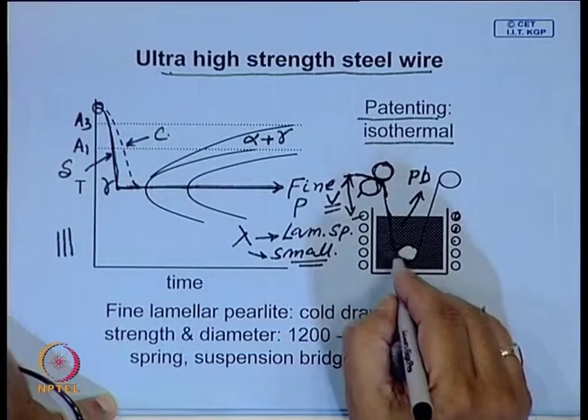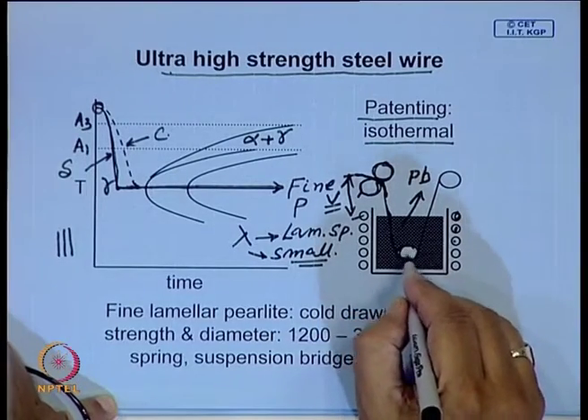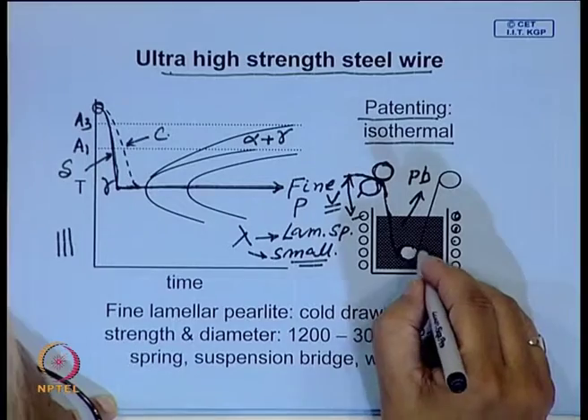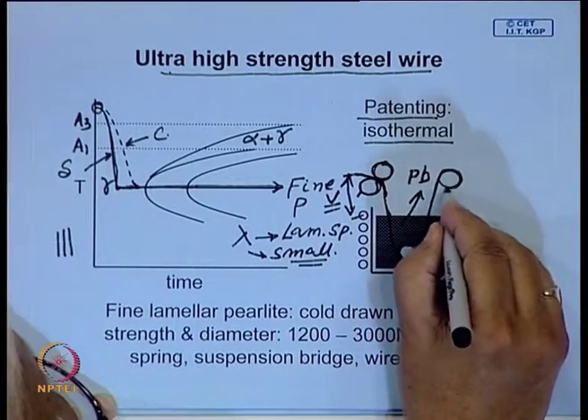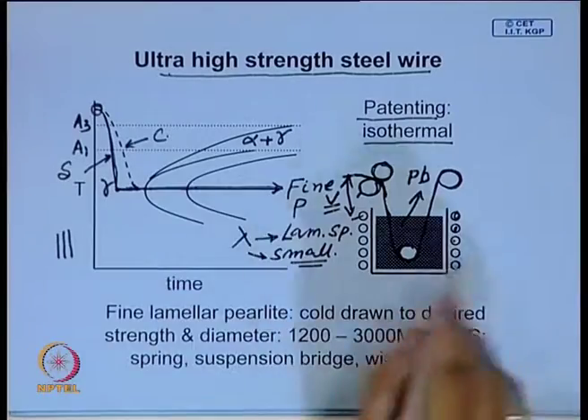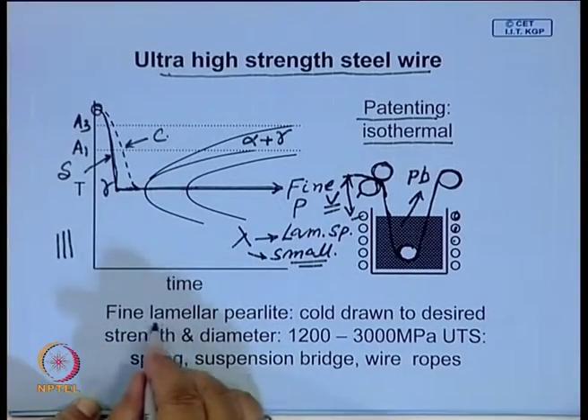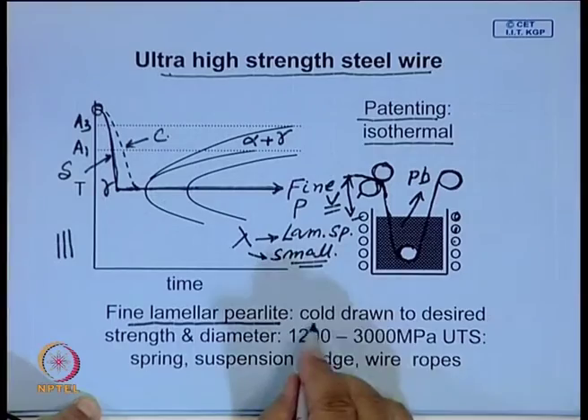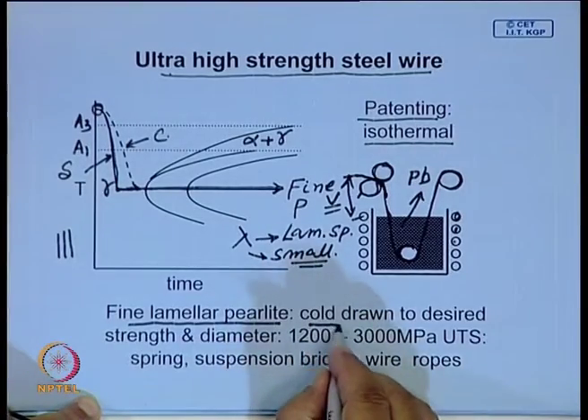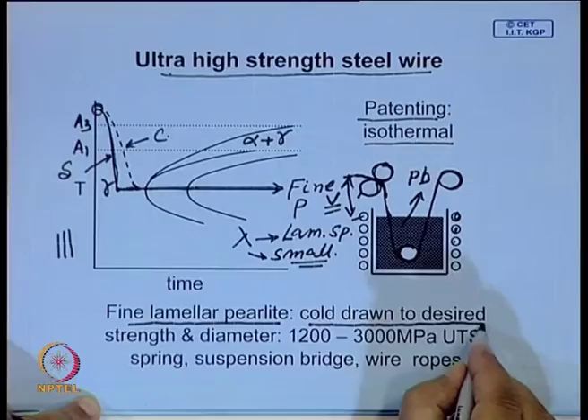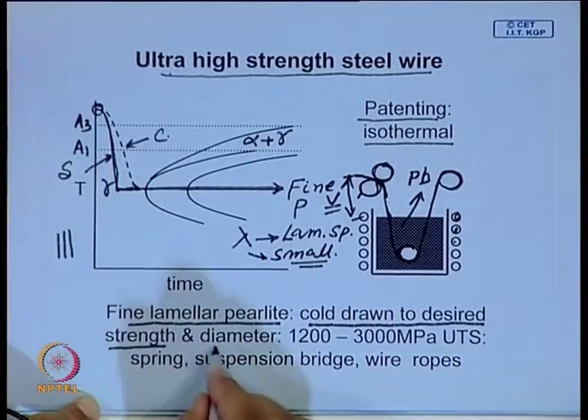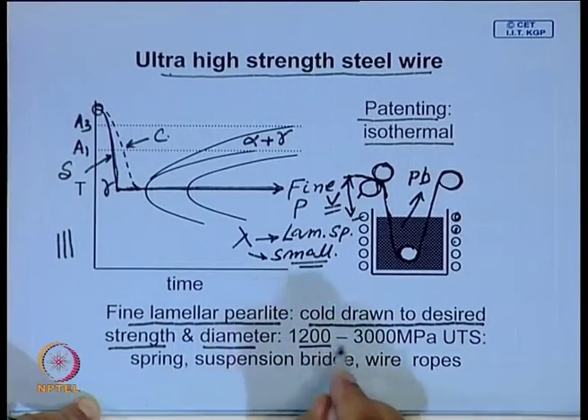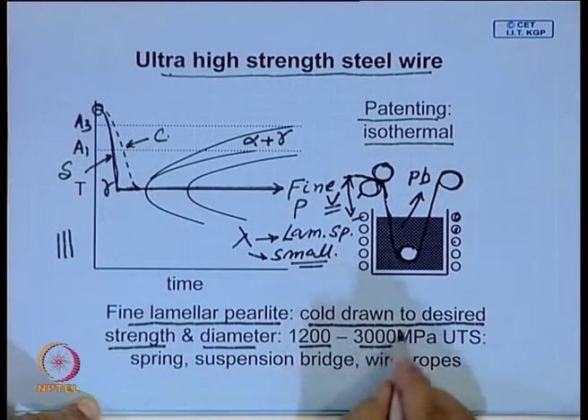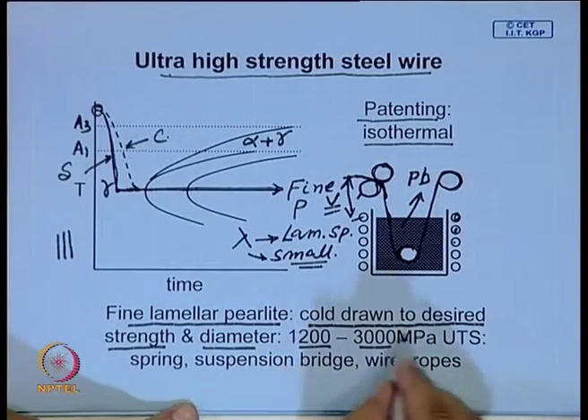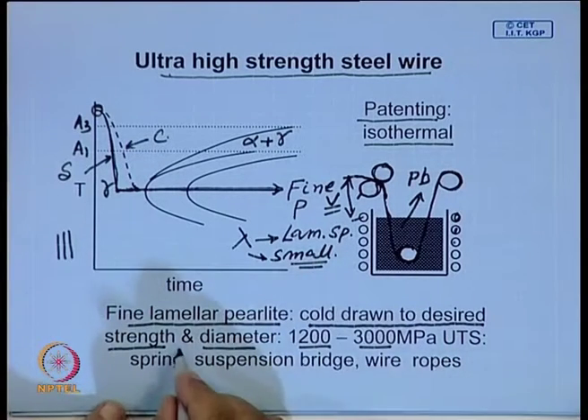It comes into the lead bath, and this is just a guide idle roll, and this wire comes out and coils here. And by this treatment it is possible to get extremely fine lamellar pearlite, and they have excellent drawing property, that they can be cold drawn to desired strength and diameter, and you can get a strength, as you can look at this, of the order of GPa, gigapascal strength you are getting, and these are used for very high strength applications like spring,